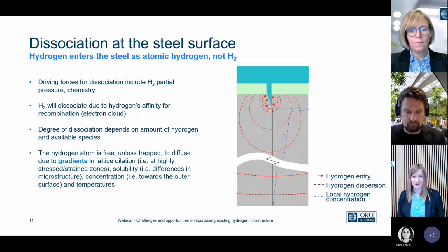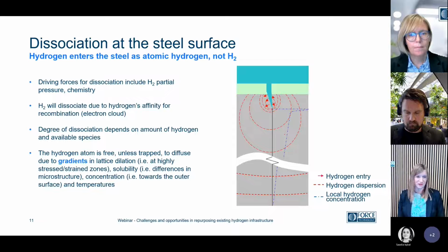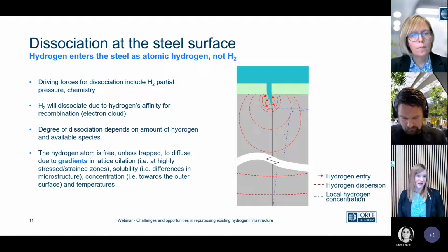Partial pressure of hydrogen is one of them. Surface chemistry. Then we may have effects inhibiting this dissociation at the steel surface. That could be a coating inhibiting the hydrogen uptake in the steel. It could also be an oxide layer and other available species near the surface. As we can see to the right, this green layer could illustrate an oxide or a coating, and the red is the dispersion of hydrogen going down into the steel.